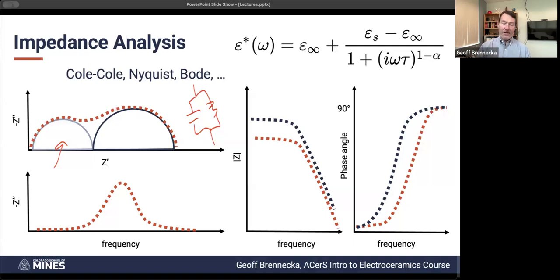Then I can start to say, if this circuit model represents my sample and it matches up with the data that I've measured, then I'm going to interpret that as the grains as a whole having this capacitance and this resistance, and the grain boundaries as a whole having this capacitance and this resistance. And so that's the super hand-wavy approach to impedance analysis, but that's basically the way that we have gradually built up an understanding of what's happening in these complex microstructures.